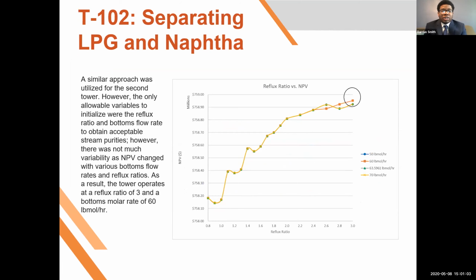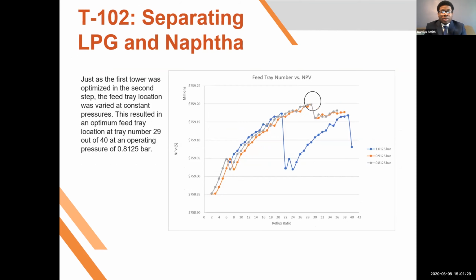Moving on to our LPG and naphtha tower, we couldn't specify the purities in that one due to convergence errors in ChemCAD. So we decided to look at our reflux ratios and our bottoms molar flow rate. There wasn't much difference, but there was an optimal point at about a reflux ratio of 3 with a bottoms molar flow rate of 60 moles per hour. And we performed the same optimization as the previous tower, looking at the feed tray locations and at the pressure. With this tower, it was actually a lower pressure that was most optimal, with the feed tray at tray 29 out of 40 and a pressure of 0.8 bar.